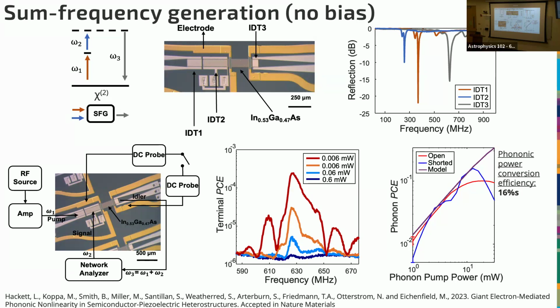If we just take this peak power right here at the peak of the conversion, and we plot that as a function of pump power, we're actually getting about 16% conversion efficiency for this signal to idler, all for phonons, right? So this is pretty good, right? Like if you go and buy a commercial crystal for doing sum frequency generation, 16% is not bad.